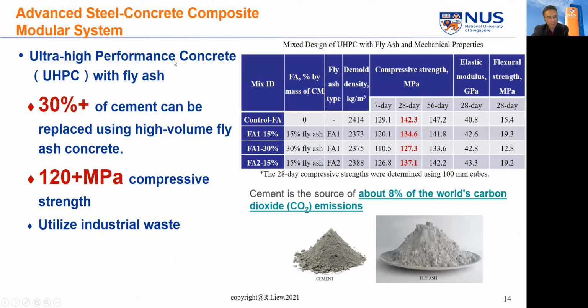So for the ultra high performance concrete with fly ash, we developed a mix where up to 30% of the cement can be replaced using a high volume fly ash concrete, where we can create up to about 120 megapascal concrete compressive strength, utilizing industrial waste. This is a typical mix design of a fly ash by percentage replacement by mass of cementitious material, 15% fly ash, and the fly ash type. This is the density of the concrete we obtain. The compressive strength at 28 days is about this level, with the Young's modulus of more than 40 gigapascal, where we use this to reduce the amount of the cement.